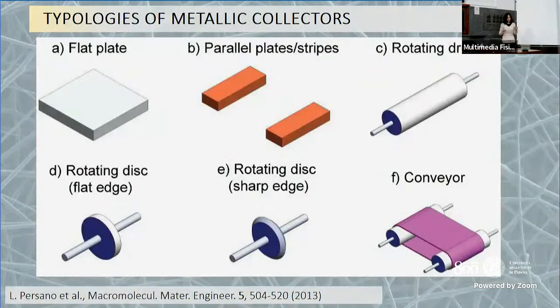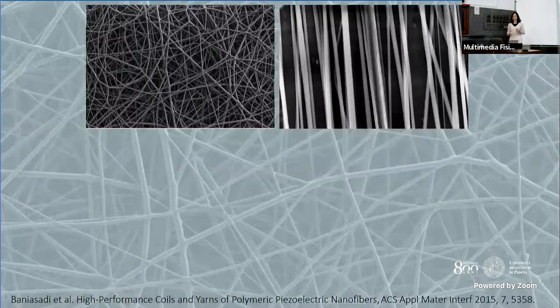Depending on the shape of the collector one is going to use, you can assemble this fiber on the substrate with different morphologies. Here I reported some representative topologies of a collector that one can use. The final result is that, for example, if you have a flat plate, you have nanofibers distributed in a random fashion. If instead you have a couple of plates with a gap in between, or a rotating collector, what you get is that these fibers can be tightly aligned towards a certain direction.